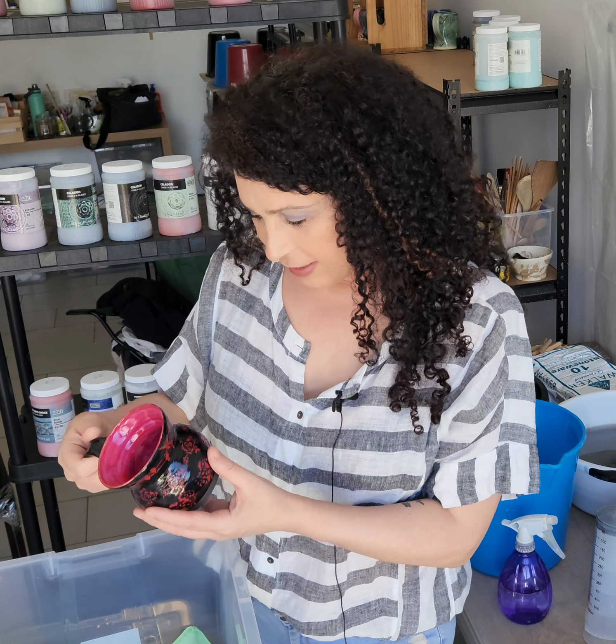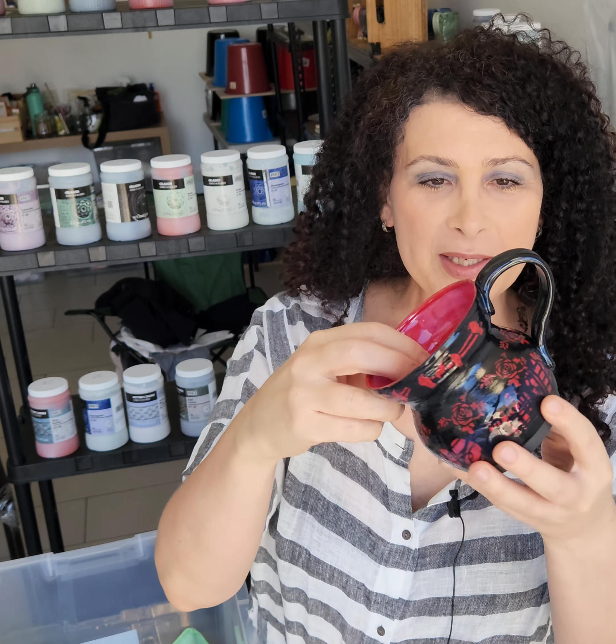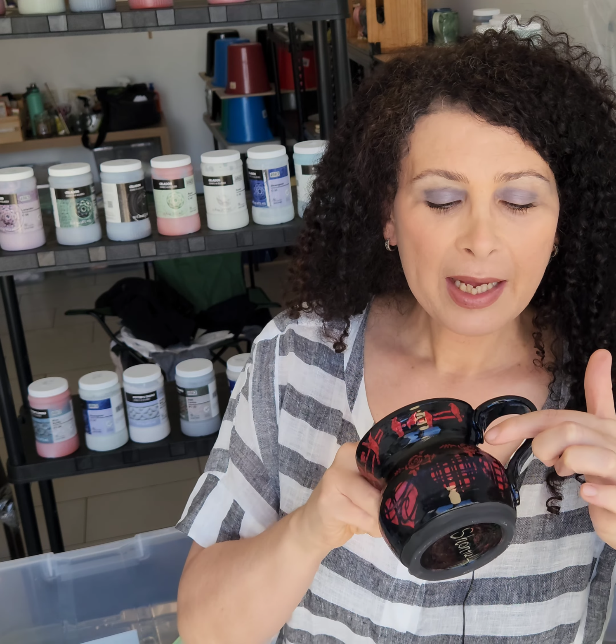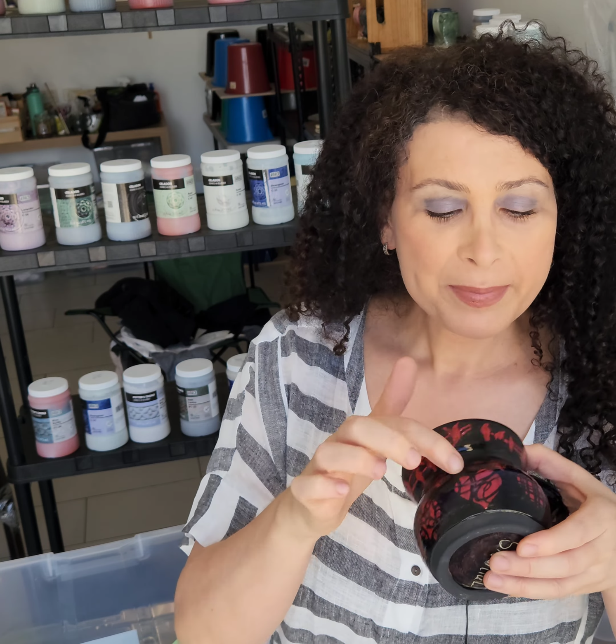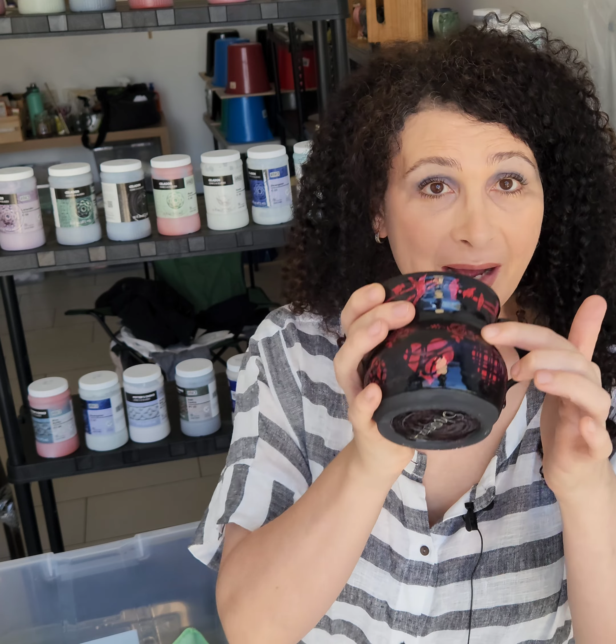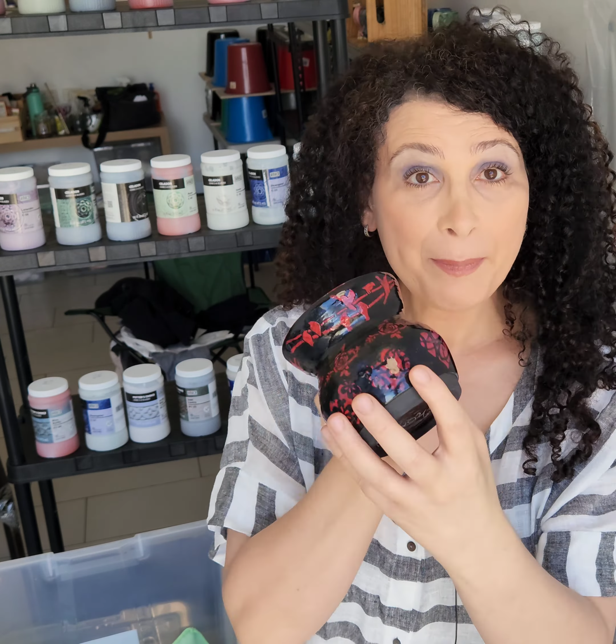Okay, and this is another repeated recipe, but this time it does look much better because the red underglaze didn't get wiped out. Last time I used normal clear, which had zinc, and that zinc in the clear sort of ate the red underglaze. This time this didn't happen. You can actually feel it with your finger. It's a raised sort of area.